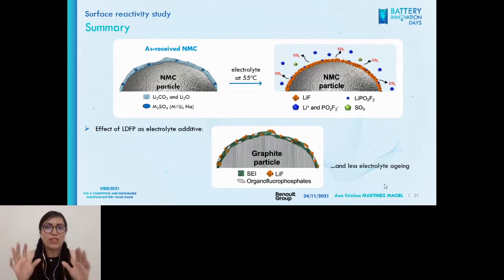This part was important for us from an industrial point of view because we are using something that was on the surface as electrolyte additive. So we don't have to add it artificially, right? It is being produced inside with the electrolyte. The additive is being produced in situ. So this was very important for the industry. We are using something that was normally deleterious for the NMC. This is why this was important.